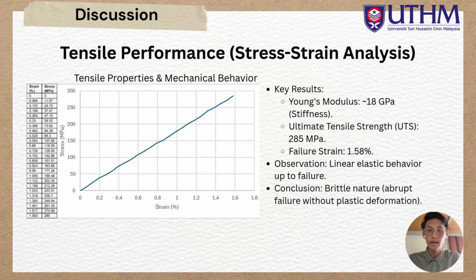Okay, now let's take a look at the mechanical data. Please refer to this figure. This stress strain curve tells us exactly how our material behaves. From our tensile test, we achieved an ultimate tensile strength UTS of 285 megapascals and a stiffness, or Young's modulus, of approximately 18 GPa, which means gigapascals.